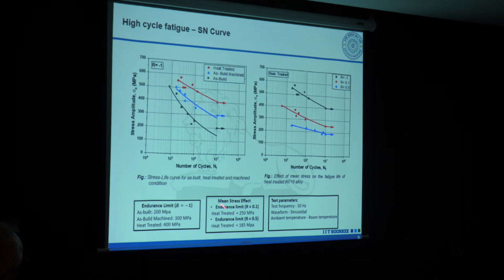In that case, we did tests at two different R ratios. The R ratio is the stress ratio, so we tested at two different stress ratios, 0.1 and 0.5. In the case of 0.1, we obtained a fatigue limit of 250 MPa, and in the case of 0.5, we got a limit of 185 MPa. All the tests were done at room temperature at a frequency of 10 Hz.